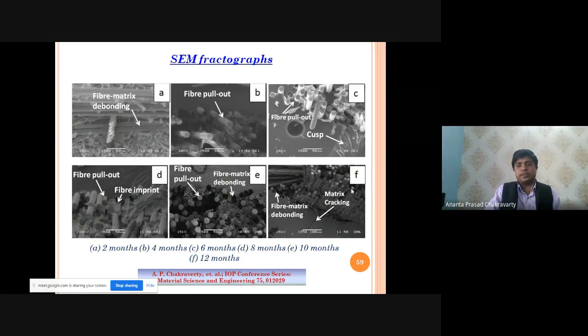That means it is so strong that all the load has been transferred to the matrix, so that the matrix will be cracked, but the fibers do not have a single fracture or single crack or breakage, as you have seen. That means the material can sustain in seawater in a very effective sense. So now this glass fiber reinforced polymer composite, with very excellent corrosion resistance, can be used as piping material, so that seawater can run inside it.